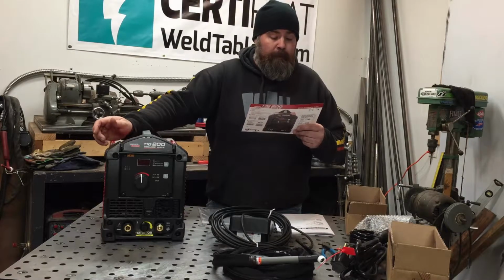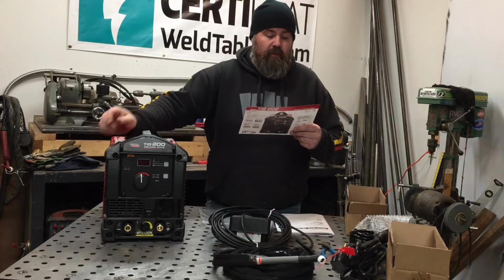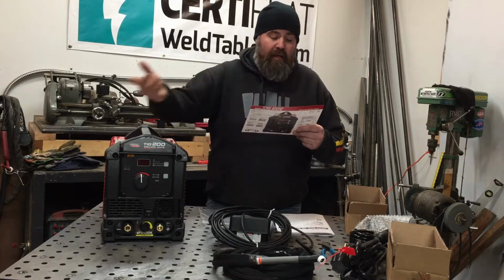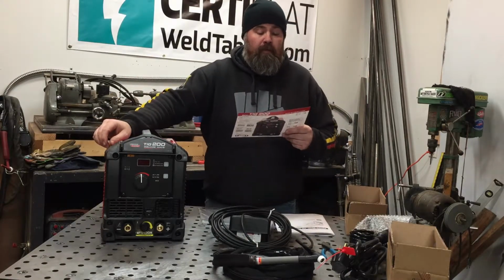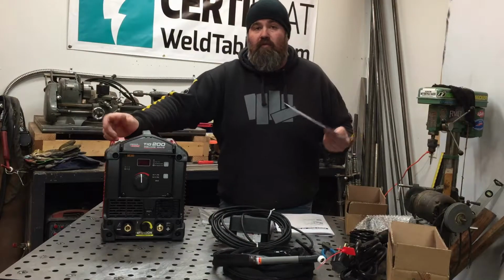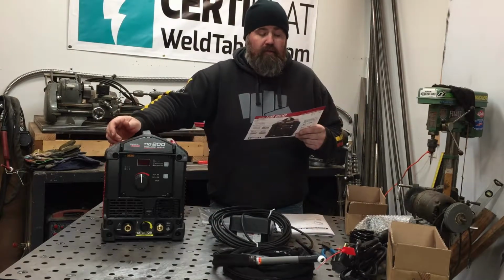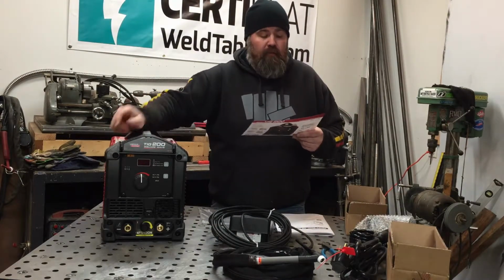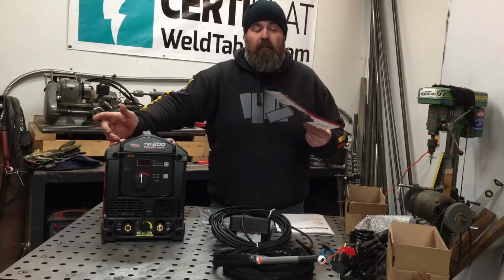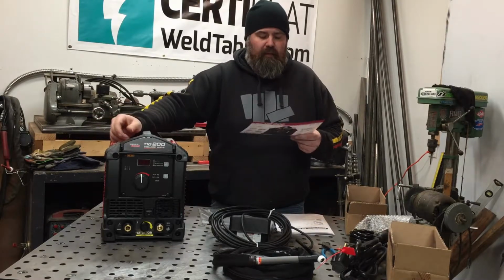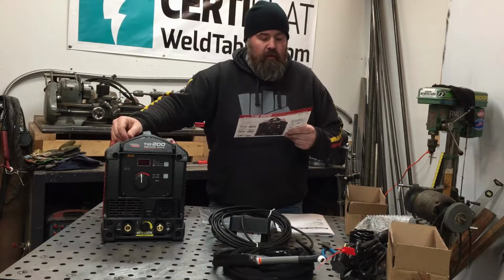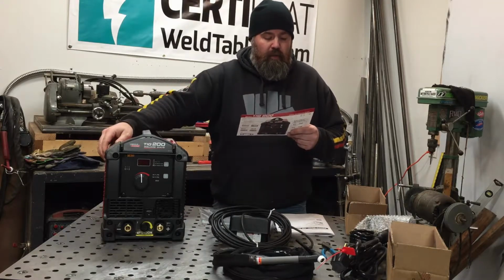10 gauge, 135 thousandths of an inch. They recommend 90 to 120 amps. So if we set the machine to 135, we might be a little hot. We could turn it down or use the foot feed, but again, that rule of thumb, I think that's fair and applies, even in comparison to their numbers here.